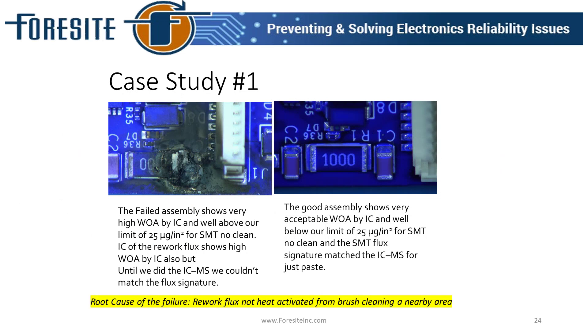The capacitor in that area is a big glob of thermally melted mess, due to the rework flux from a nearby part that was brush-cleaned into this area. The primary power pin coming into the device set up this catastrophic failure.